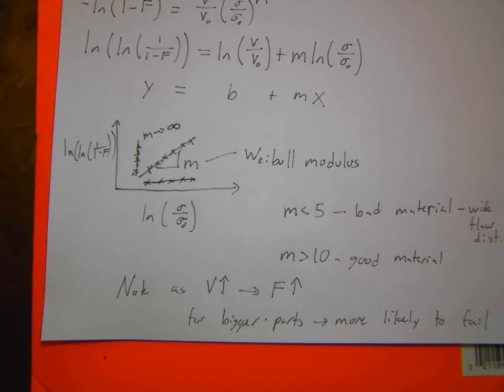If I look at, I think one of the particularly bad ones was tungsten carbide, which is incredibly strong but incredibly random. So I think, there we go. This has a Weibull modulus closer to like 5-ish, but an average critical stress, something like that, a little bit less. Yeah, close enough. So this has an average critical stress now of 1600, so 1.6 gigapascals, but it has a Weibull modulus of like 5.